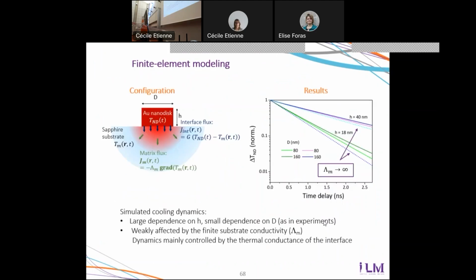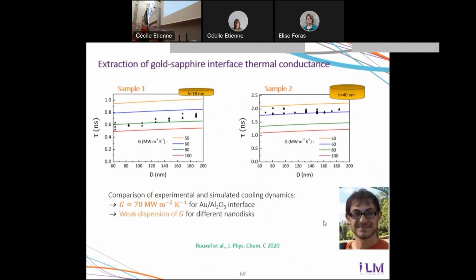So by comparison with simulations, we could extract the thermal resistance of each measured nanodisk. It was seen to be very close from one nanodisk to another in the same sample. And we had a slight difference: it was slightly higher for the second sample, because the contact between the objects and their substrate was slightly different for the two samples that we used. And this was one of the results of the PhD thesis of Romain Rouxel, who defended 2 years ago.